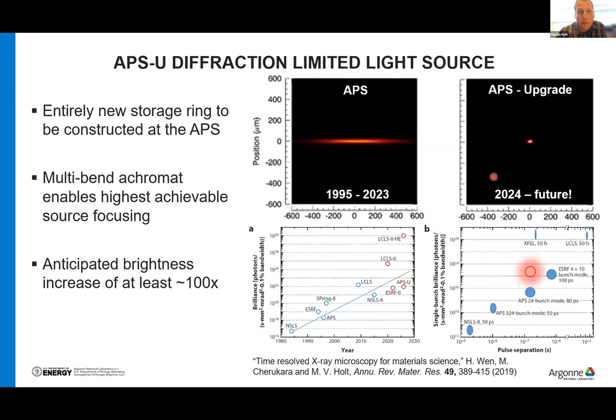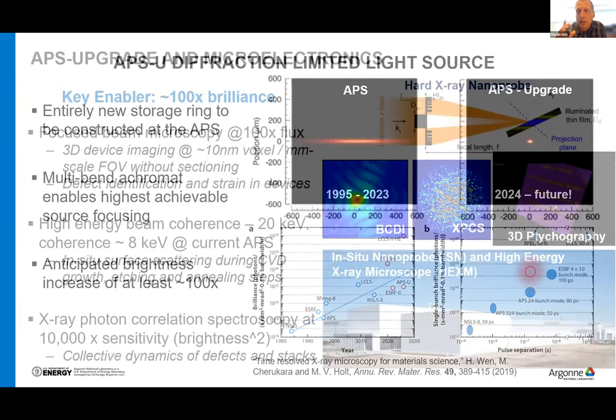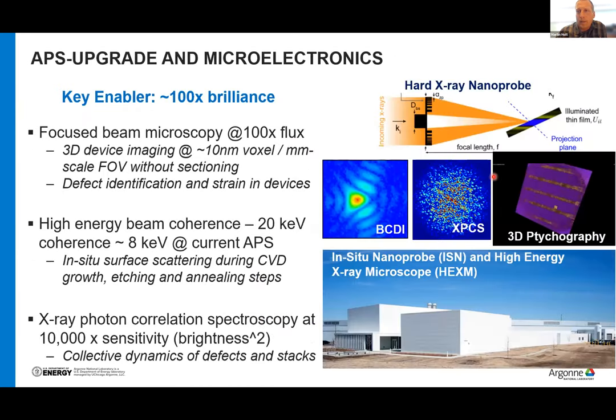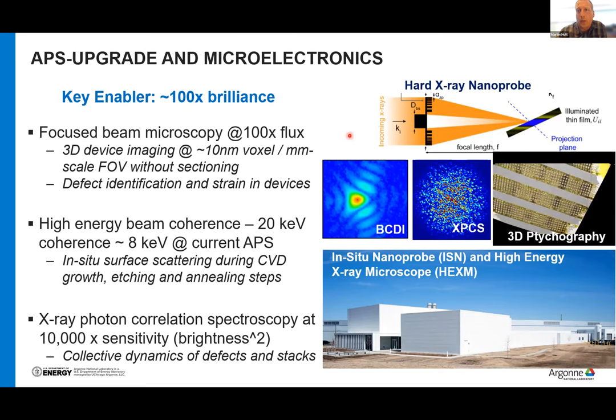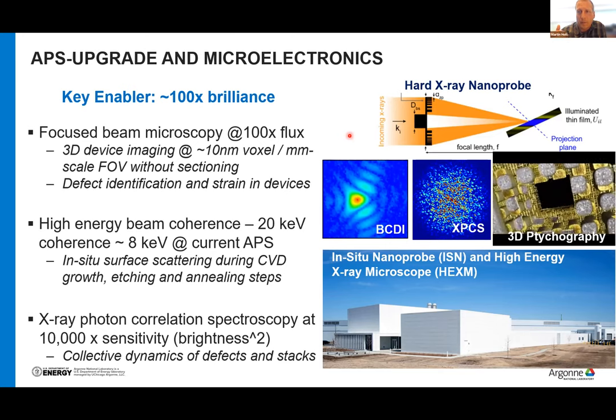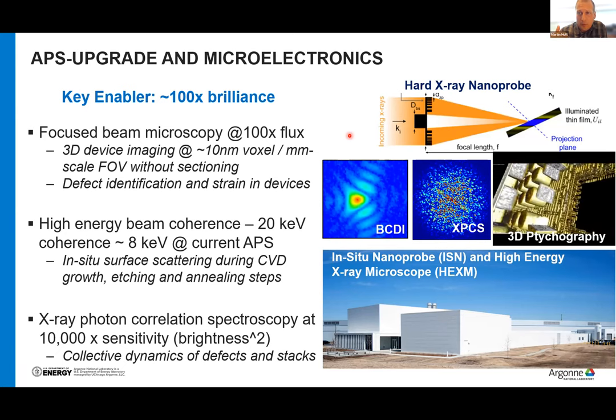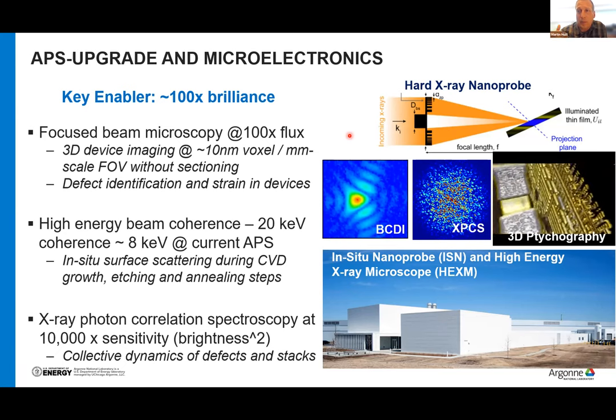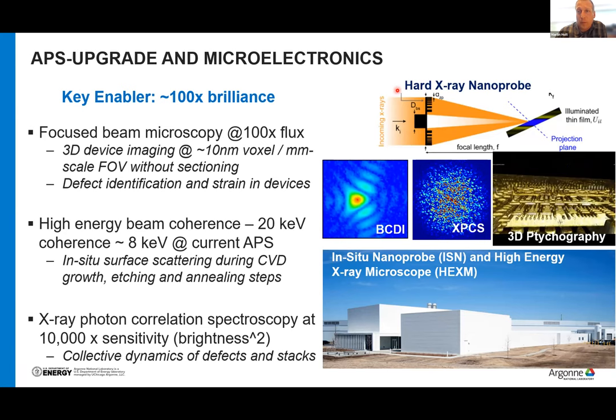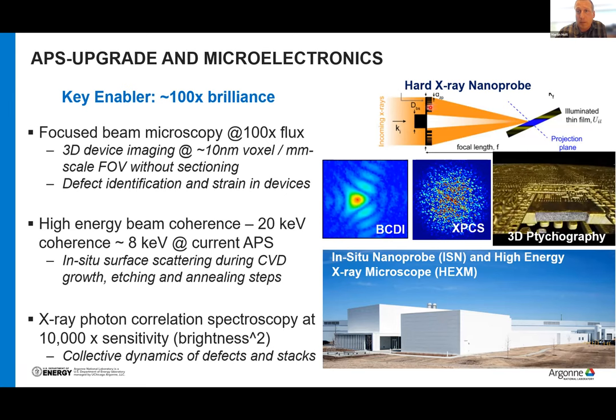Obviously all these things are going to get 100 times better due to the brilliance, but I did want to amplify what it is that brilliance actually gets you. It's 100 times increase in beam coherence, and coherence is the ultimate driver of these imaging methods. It's the fidelity by which real space perturbations can be encoded onto an X-ray wavefront. And we use that in multiple different ways. We use diffractive optics to focus our beam down to a 20 nanometer beam spot using these 15 nanometer, well, actually 10 nanometer now, outermost zone plates here at the nanoprobe. This will get 100 times better.